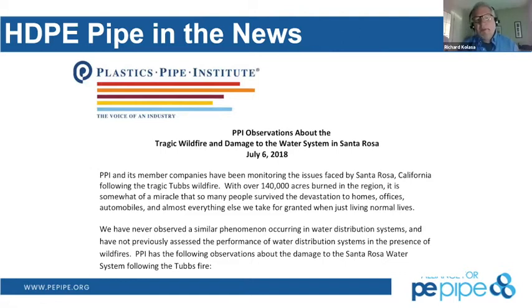We insert this slide here for the materials because the Tubbs fire in Santa Rosa, California, really created an interesting development. They had a few water lines placed above ground because they didn't want to disturb the forest or the green spaces that they were going through. Unfortunately, the green spaces burnt, and so did the polyethylene. There were some accusations around benzene generation, but polyethylene does not generate any type of benzene. It's hydrogen and carbon. The benzene was from external sources that were found at a later date. Those studies have been conducted, and you can read further on these observations by PPI.